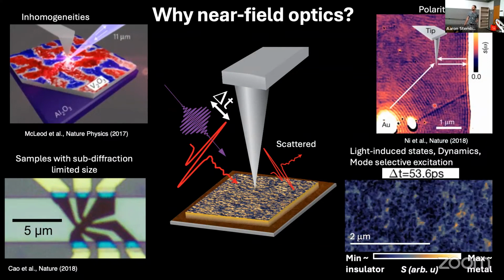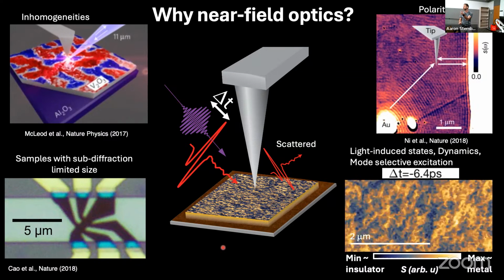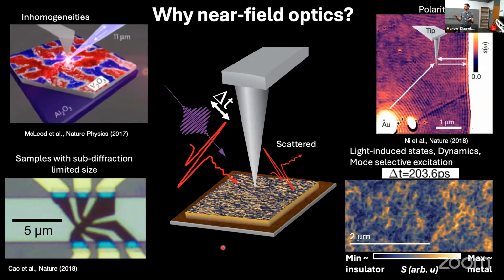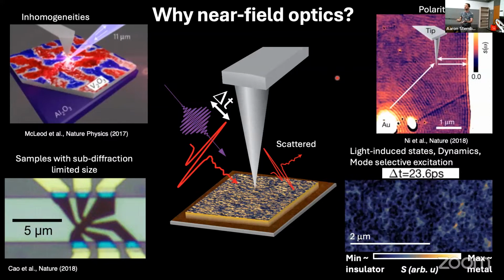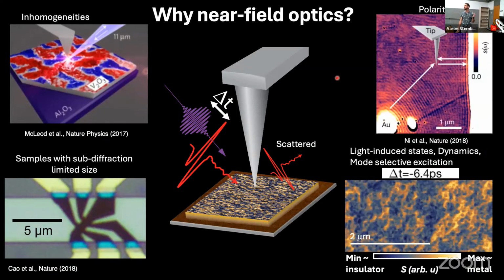Explain why the resolution is independent of the wavelength. Well, the short answer is that the infrared light comes in and it polarizes the tip, and there's an evanescent field at the apex of the tip, which is confined to the tip's radius of curvature. And this near field is isolated from background radiation by tapping the tip up and down. We demodulate the scattered signal at harmonics of that tip tapping frequency so that we can essentially pluck out the component of the field that is evanescent or localized to the radius of curvature of the tip. And while the ratio of that field to background may be somewhat wavelength dependent, the resolution that we get after performing this procedure is not. We get resolution that is given by the radius of curvature of the tip, independent of the wavelength of incident light.